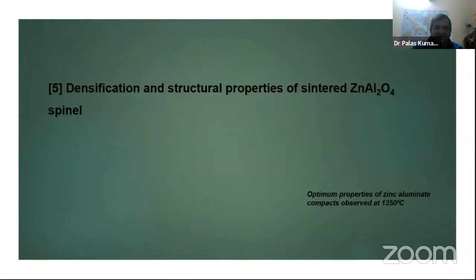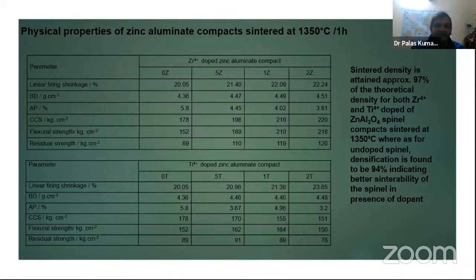Now, coming to the densification and structural property of the sintered matrix. I already mentioned that the optimum property of the zinc aluminate compacts is observed at 1350 degrees centigrade. So here we consider only this one temperature, we do not display the other temperatures. So this is the table of physical properties of zinc aluminate compacts. Here we see the linear fire shrinkage, bulk density, porosity, CCS, flexural strength, and residual strength for both titanium and zirconia group. And it is quite interesting that sinter density reaches up to almost 97% of the theoretical for both zirconia and titanium. The theoretical density of zinc aluminate is 4.63 gram per cc, and for undoped, we achieved 94%. So it indicates the better sinterability of the spinel in presence of the dopant.